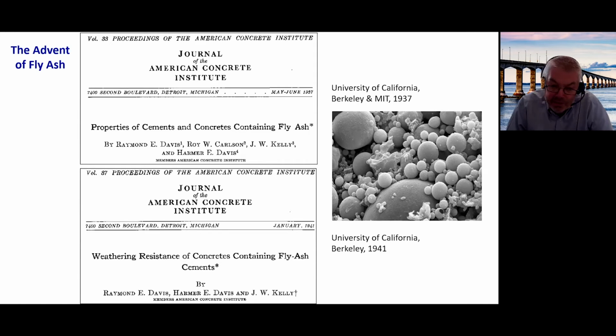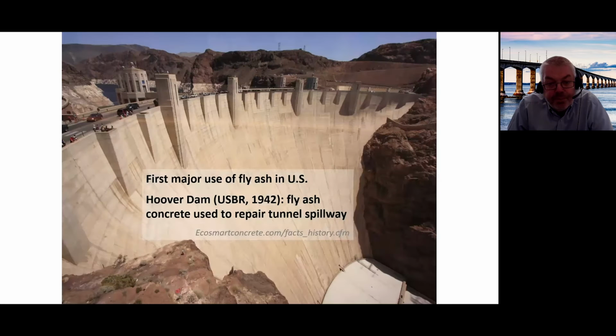And the economics of this meant that fly ash slowly became the dominant pozzolan for the second half of the 20th century. The first major use of fly ash was in the repairs done to the Hoover Dam. It wasn't used in the main construction of the Hoover Dam. That was built a little bit too early for that, but it was used for some major repairs to one of the tunnel spillways.